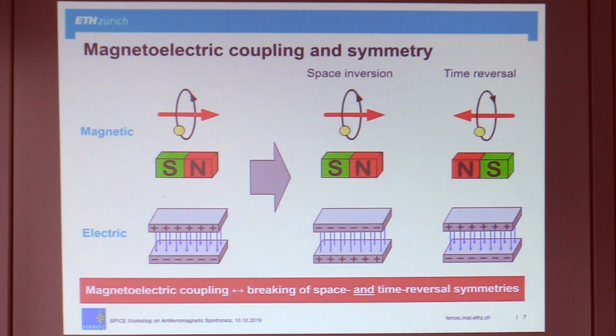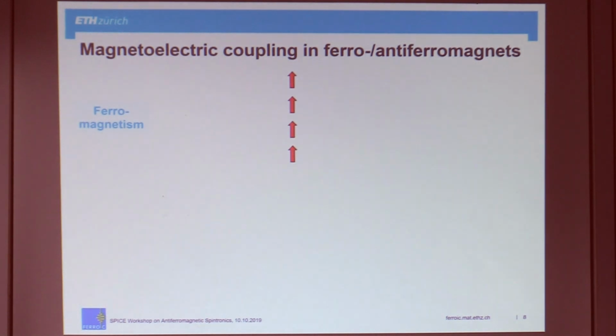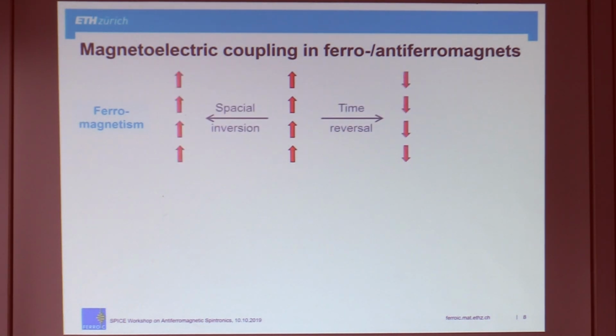Okay. Now let's look at ferromagnetism and apply time reversal and spatial inversion. You will see that time reversal is indeed violated, so all the spins are turned upside down. Time reversal is not a symmetry operation for a ferromagnet, but in general, spatial inversion is. So ferromagnets are not per se a good candidate if you look for magnetoelectric coupling effects.